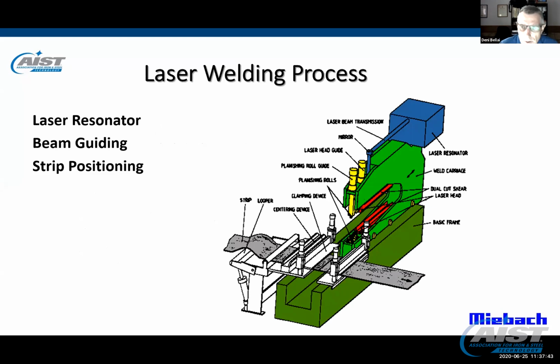Laser welding is similar to seam welding or resistance welding that Blake was just talking about. The strip still needs to be positioned with a pinch roll and centering guides. So it's very much the same in that way. The ends of the strip still need to be cut and squared off in preparation to be joined. The differences come in the geometry of the cuts and the type of energy used to fuse the material together. In laser welding, the heat source is derived from focused laser light energy. The profile of the cut needs to be extremely square.